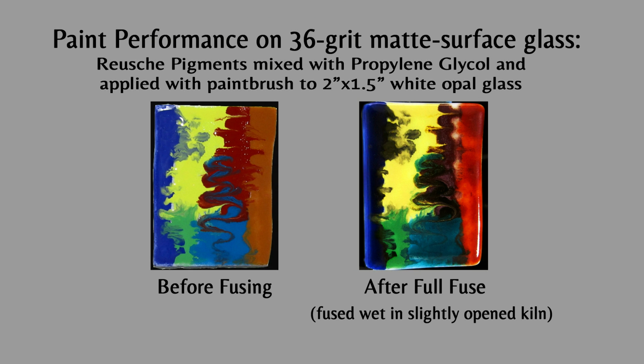Here's a small test piece that I painted with Reusche pigments mixed with propylene glycol using a method that I describe in my website blog. After applying the paints with a paintbrush, I used the opposite end to drag the paints back and forth into each other. Propylene glycol as a medium creates a thickness similar to oil paints, so they cover well, although they do take about a day to dry. Being impatient, I went ahead and fused this piece wet with the kiln lid propped open about 1/4 inch. As you can see, the 36 grit matte surface allows the retention of quite a bit of detail.